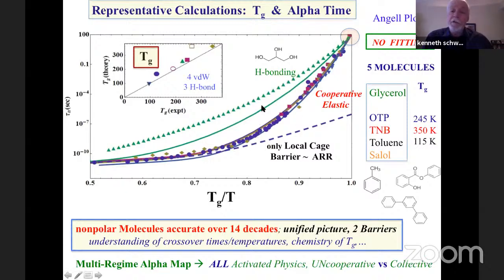And since part of me is a physical chemist, I was happy to see that the ideas do not work as well for hydrogen bonding systems. That is, mapping a hydrogen bonding system like glycerol to an effective hard sphere must be a more severe approximation. So we conclude that for nonpolar molecules, the theory is quite accurate over 14 decades. It allows us to have a physical understanding of the crossover times and temperatures. We're able to predict Tgs almost quantitatively. And so ultimately, there's a multi-regime alpha, the whole alpha map, we believe, reflects this different alpha.